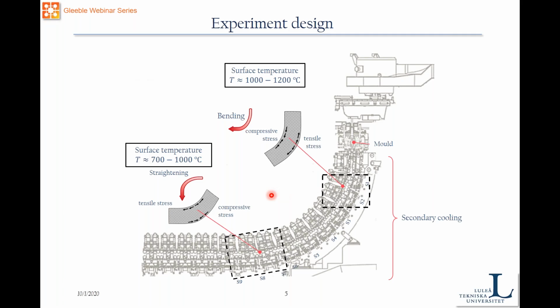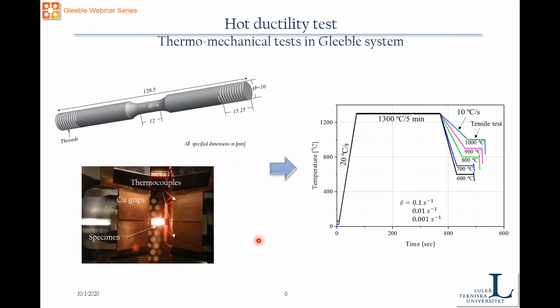What we did is important to mention just before the experimental part. The temperatures that you can see here are the actual temperatures that were possible to measure by installing pyrometers in the caster. By taking these parameters together with the casting speed in the process, it was possible to simulate the process as close as possible to reality in solid state with the Gleeble system. We were using this type of specimen with a diameter of 6 millimeters and a gauge length of 12 millimeters.